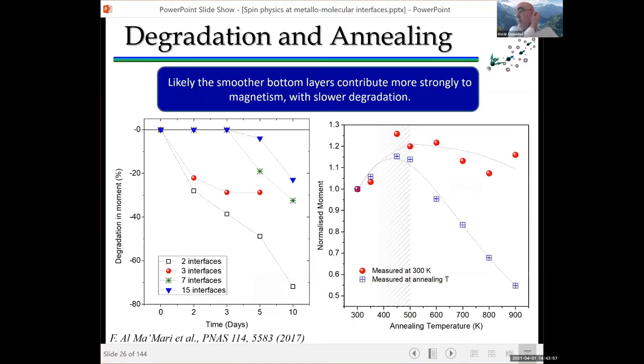The other thing that is very characteristic of molecular structures in general, and these ones in particular, is that they degrade very quickly. One has to be very careful with how one measures. Obviously, the oxidation depends on how thick your sample or your total sample is. The more interfaces you have, the longer it takes to lose your magnetization. But typically, in about a couple of weeks, most of your magnetization is gone.